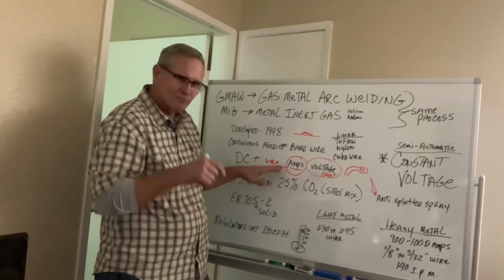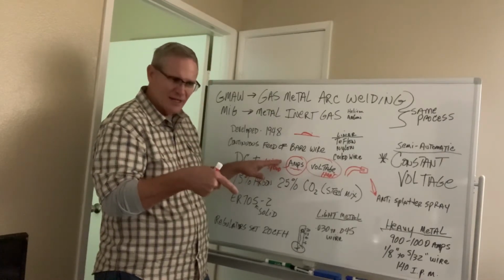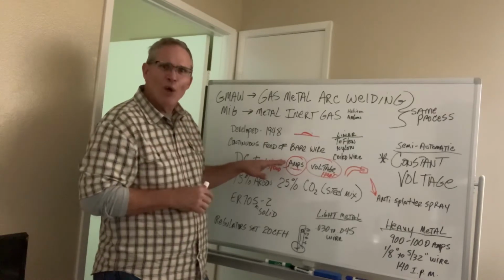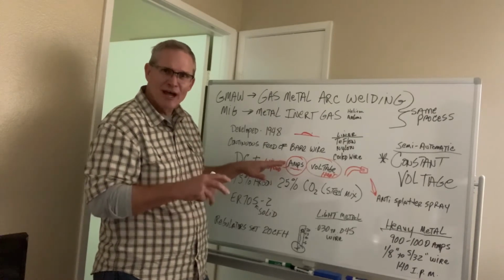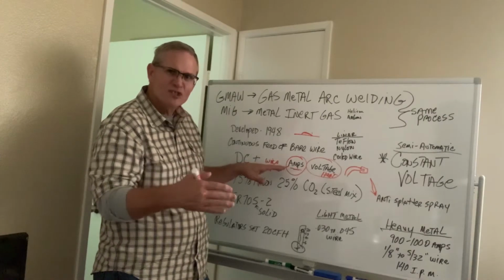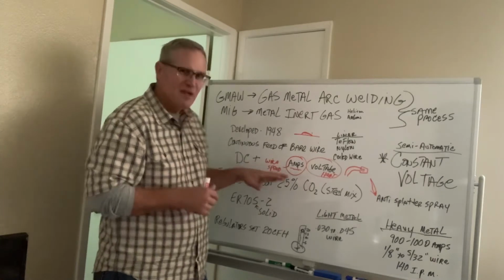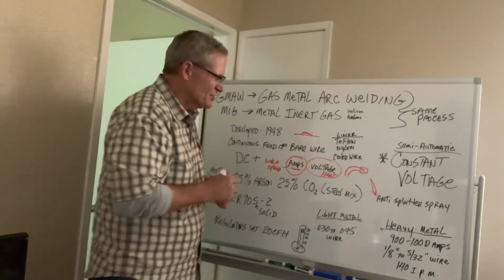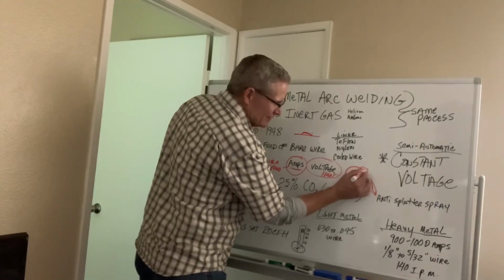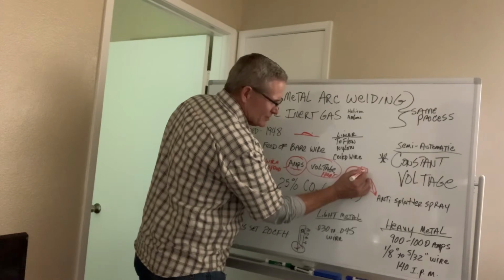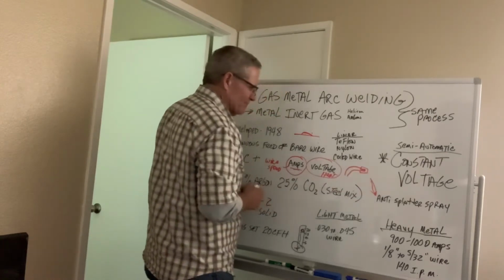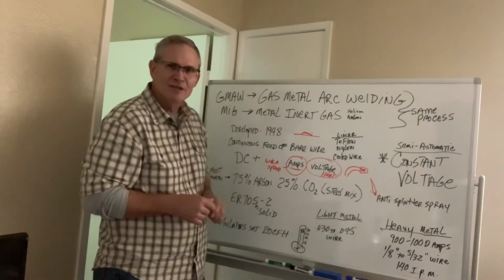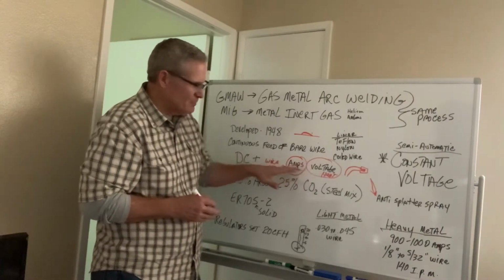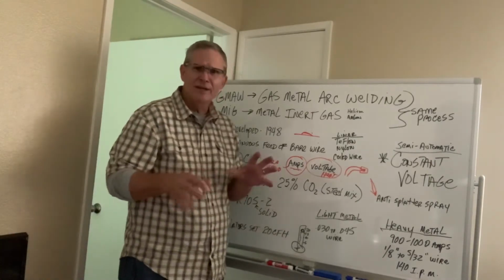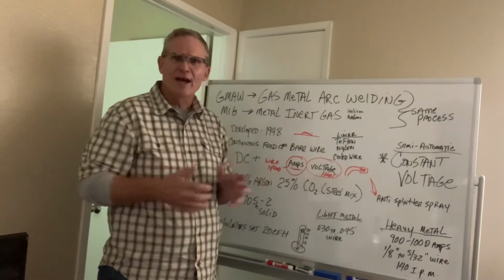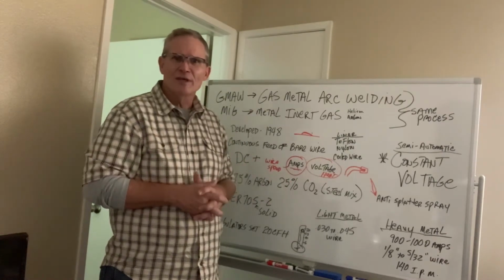On the wire speed, if the weld gun itself is kicking back at you, your wire speed is too fast. You need to turn down the wire speed so that it moves smoothly. If your wire speed is too slow, it will actually burn itself right back into this contact tip, right in this area. It'll actually burn and do some damage to the contact tip. So that's one of the signs of it being too slow of a wire speed. But there's a balance between these two. Once you get it dialed in, usually you have a scrap piece of material and you work at it. Once it's working properly, it's really, really easy to work with.